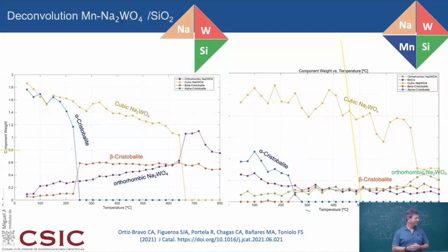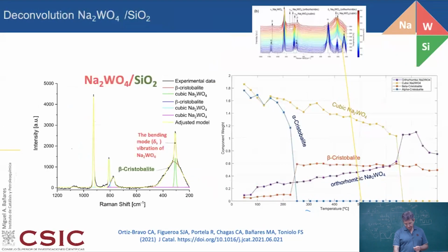Questions, I mean. This one, the tungsten oxides we have, exist in two symmetries, for example, tetrahedral and octahedral. But when you add the sodium into that, the tetrahedral phase is stabilized. Yeah, because you get the tungstates that have a tetrahedral environment. So what is the role of sodium so that it stabilizes the tetrahedral, not the octahedral?